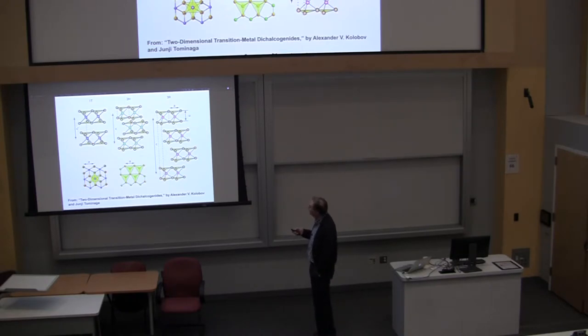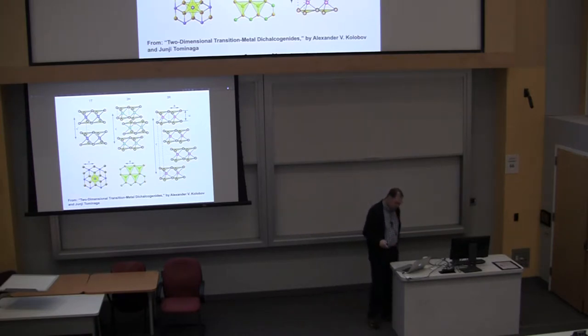So the 1 stands for 1 layer per unit cell. The T is tetragonal. This is 2 layers per unit cell. H is hexagonal, 3 layers. R is rhombohedral. So these are octahedrally coordinated, and these are just trigonal prismatic. The structures are fairly simple, but just the stacking and everything changes the properties quite a bit.